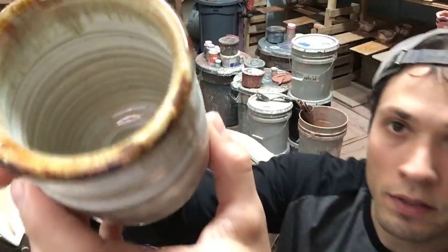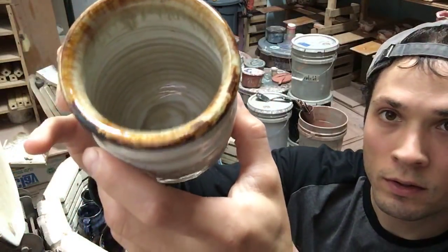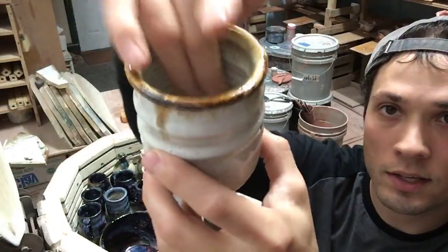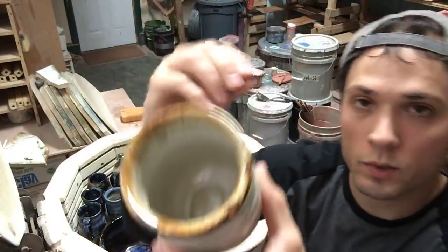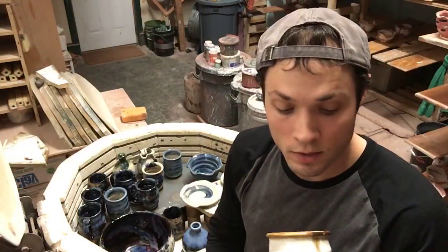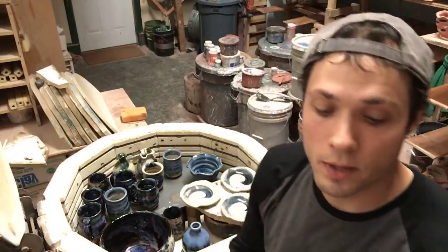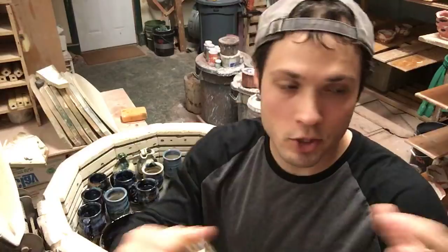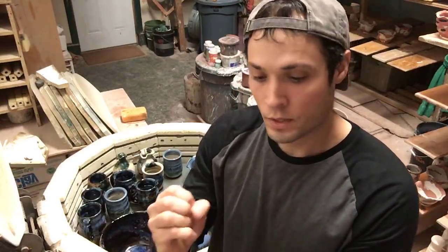On the inside, the glaze is thinner. See how I can see more of the clay color down there? The glaze was not as thick, and there's no bubbling. So by thinning the glaze out, I don't get the bubbling, but it also changes the color. You see how every time you change one variable, other things happen. What causes the bubbling? My guess is it's because the ashes have a lot of volatile ingredients that burn out.